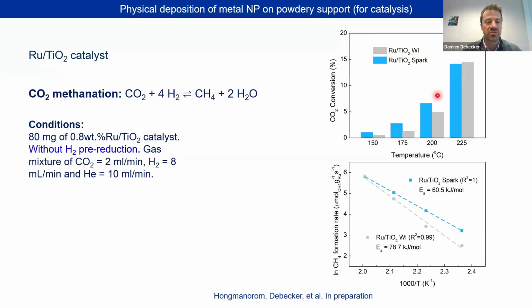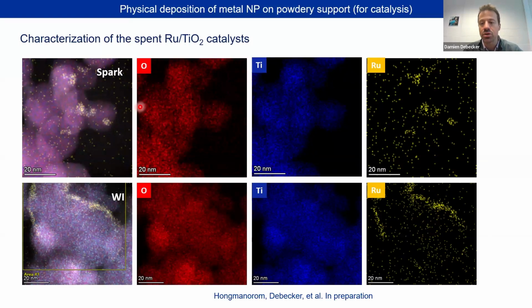We have expanded the scope of investigation towards ruthenium, and with ruthenium, it's even better, because ruthenium does not even need any pre-reduction in the reaction. It's readily active. At high temperature, it starts to be on par with the reference catalyst, but at lower temperature, it's significantly more active. We also see a slightly lower activation energy that we think is due to a better dispersion of tiny ruthenium particles on the support instead of patches, as we see in wet impregnation. This is in preparation on my slide, but actually it has been published in ChemCatChem two weeks ago or last week.